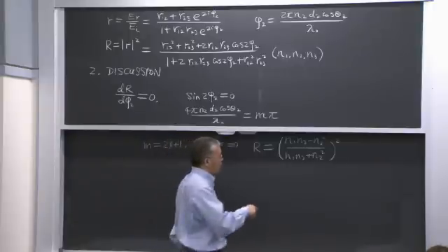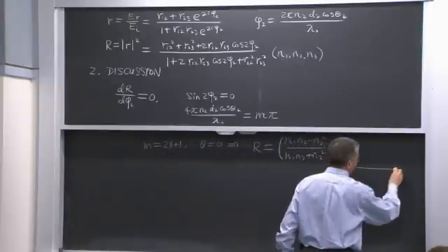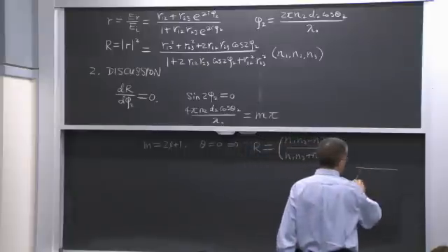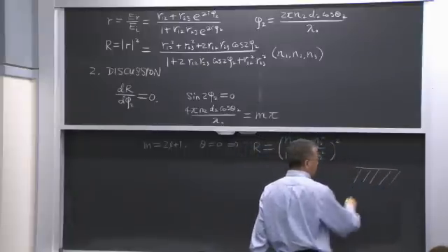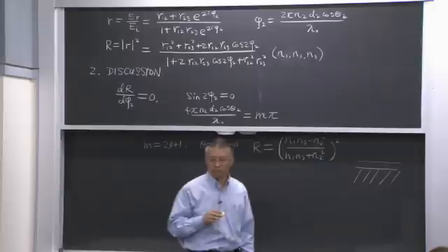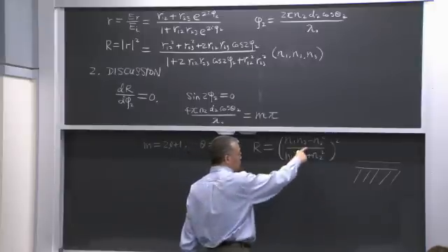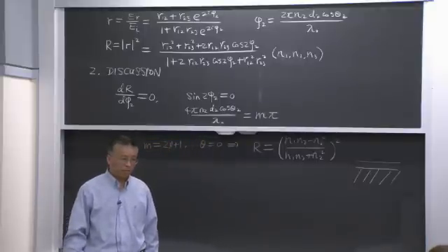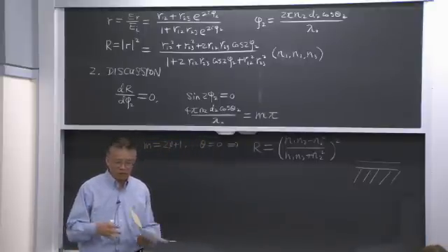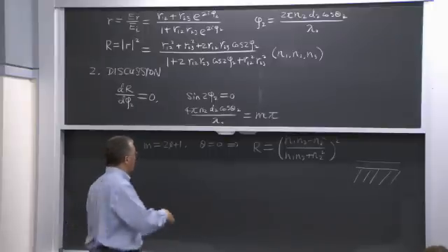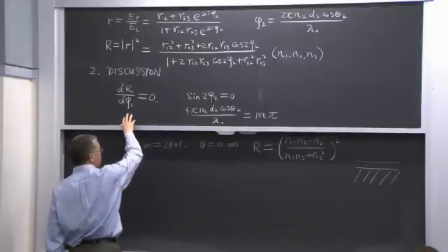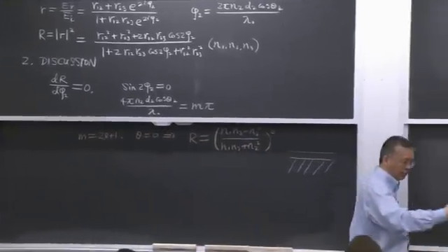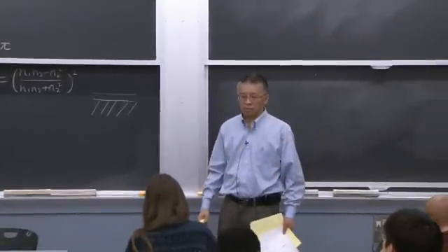You can see how I do an anti-reflection coating, right? I have a surface, and I don't want any reflection. In this case, I add a layer in between, n2. And you can say when n2 is the square root of n1 n3, you get zero reflection, right? So by using the interference phenomena, this periodic variation of reflectance is the interference of light. You can have maximum reflection and minimum reflection.